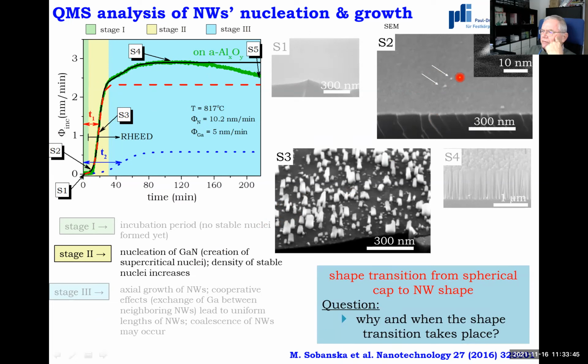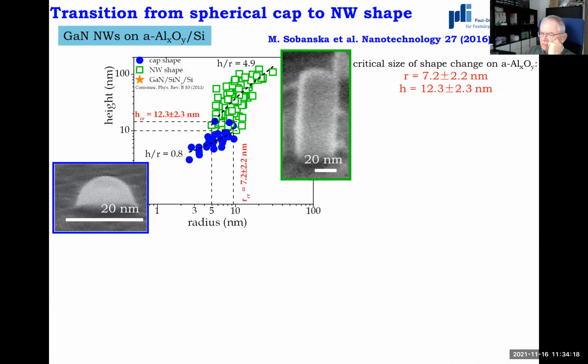These are again the same images of these two samples, where growth was terminated during the nucleation period. At the very beginning of nucleation, you see that the nuclei have the shape of a cap, and then the density of wires increases. Some of them already have the shape of nanowires, meaning on the same piece of the wafer we can see both these cap-shaped islands and nanowires, meaning there must be a shape transition from one shape to the other.